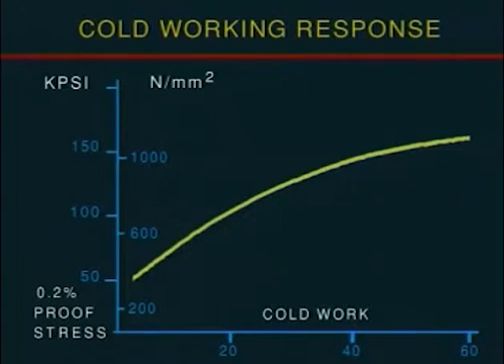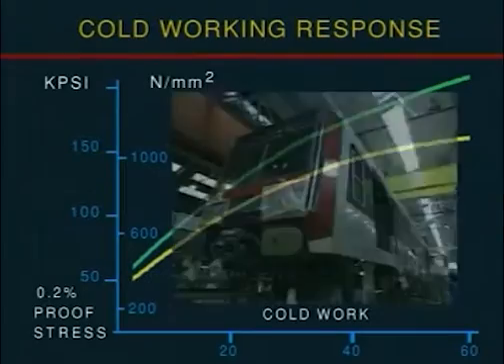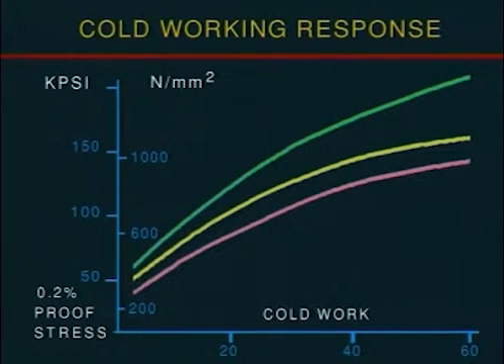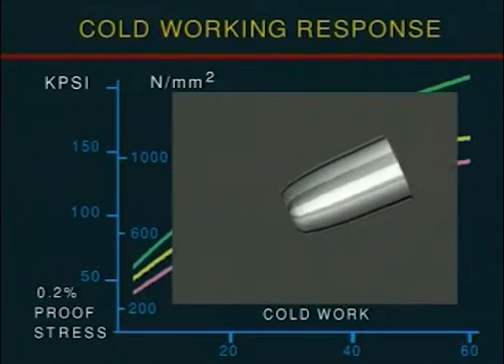The response to cold-working can be increased by altering the chromium and nickel content, and this type of higher strength steel was used for Eurotunnel vehicle wagons to obtain a more cost-effective lighter design. Alternatively, the composition can be adjusted to reduce the cold-working response, allowing components to be made easier and cheaper. For instance, this piece of steel can be made into a pen body like this by one continuous sequence of pressings, because it remains ductile and soft enough at each stage to accommodate further deformation.